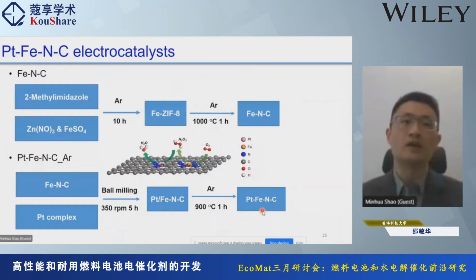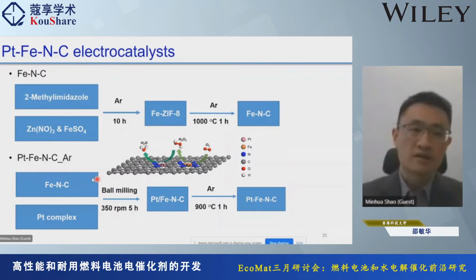Okay. So first, we design some synthesis methods for the iron nitrogen carbon, using this ZIF8. Okay. So we partially dope with iron, and then do heat treatment. You get this iron nitrogen carbon support, and then we mix in some of this platinum salt. Okay. Do the ball milling. Okay. So you incorporate some of the platinum in this carbon, and then do the heat treatment in argon again. So you get the platinum and iron nitrogen carbon mixture.